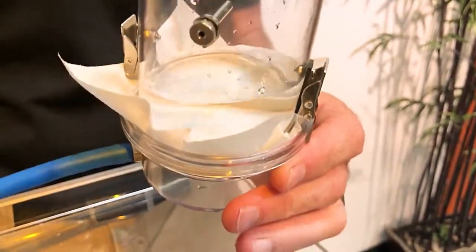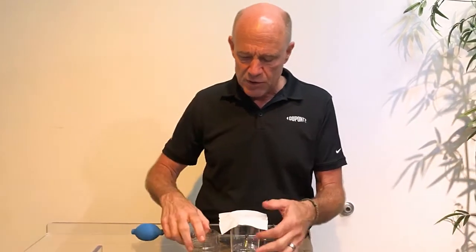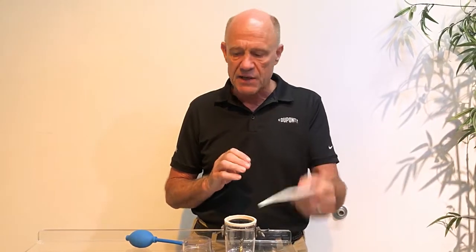The reason it's breathing is I've compromised the protective layer that's on the surface of that material. And over time, water will come through the bottom of it as well. So microporous film — not only is it not breathable, but the protection that you count on to keep your worker safe is a very, very thin layer of plastic, which is very easily damaged.